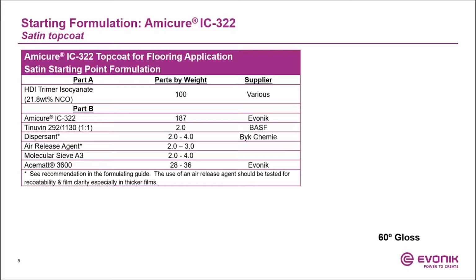Now I'm going to talk about the unique feature of polycarbamide, which is the ability to get down glossing. In this case, what you're using is Amicure IC322, for a satin top coat application. Again, it's a simple formulation. Part A is a polyisocyanate HDI trimer. Part B is Amicure IC322, again with the optional UV stabilizer. A dispersant can be added, along with an air release agent and molecular sieve, and then a key ingredient here is a matting agent to down gloss. Here we have AceMatte 3600, which is an important matting agent. It works really well in the system to get it down to a satin finish.